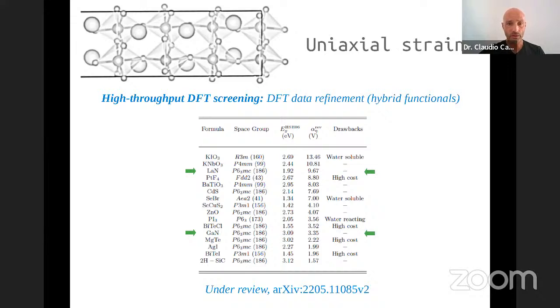On the other hand, we also identify these simple nitrides, like lanthanum nitride and gallium nitride, which are also quite suitable in terms of band alignments tunability. They're also quite simple in terms of the structure, etc. And their band gap seems to be pretty good. Gallium nitride probably is too large, but the lanthanum nitride is probably not as well known as gallium nitride, because this is very well known in the context of LEDs. But this one is not so well known, but according to our calculations, it seems to be more suitable for this piezo photocatalytic application.